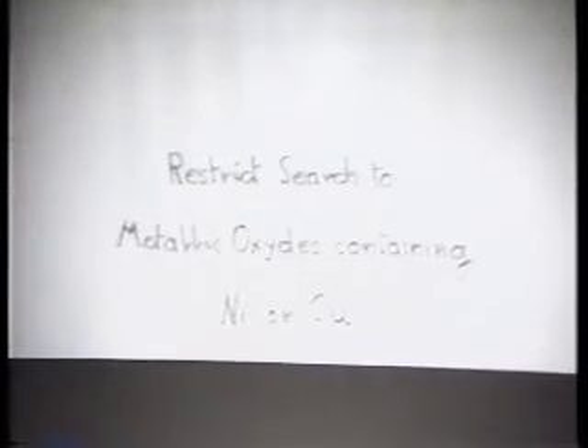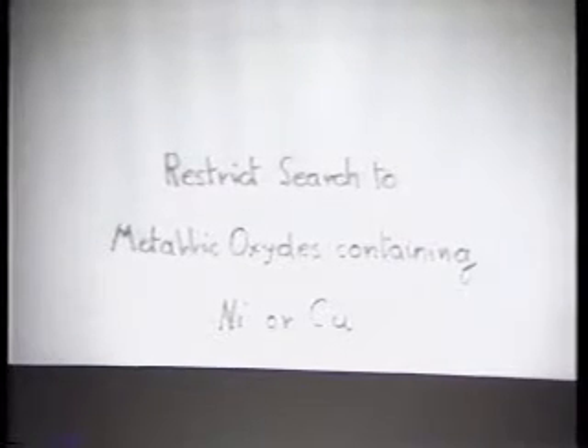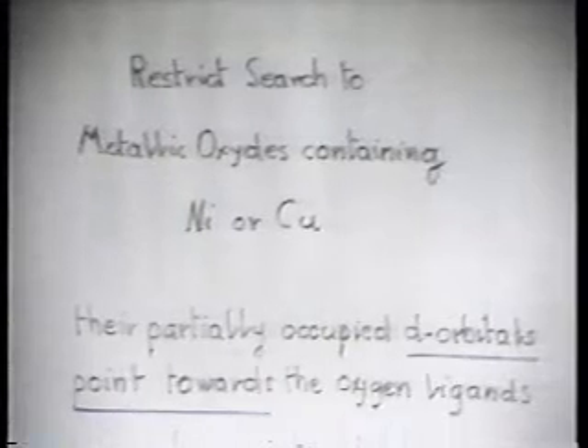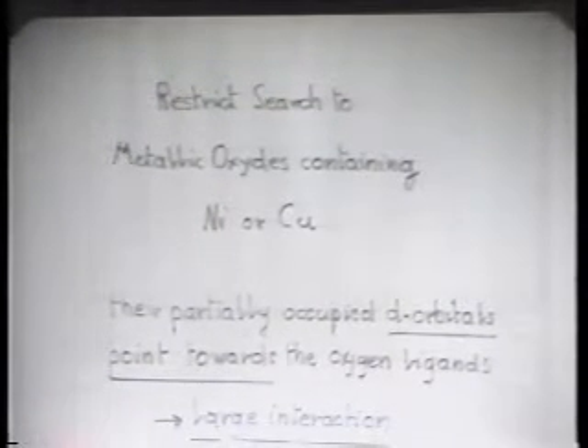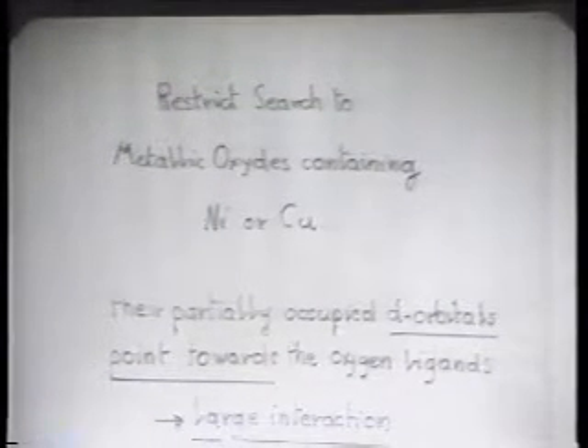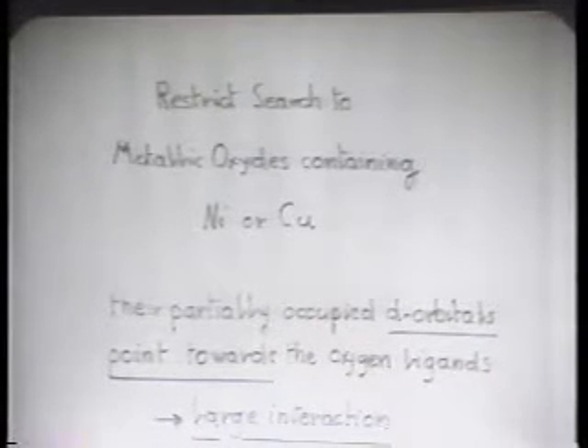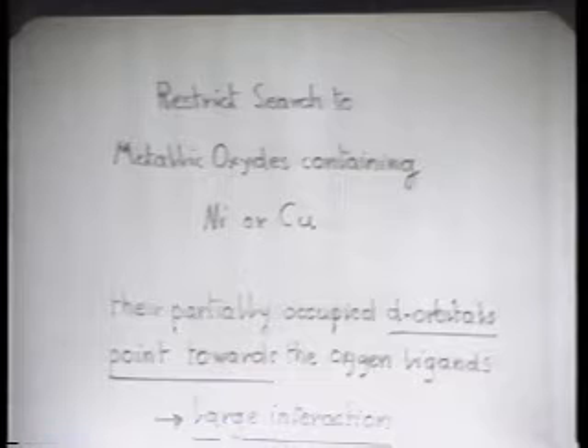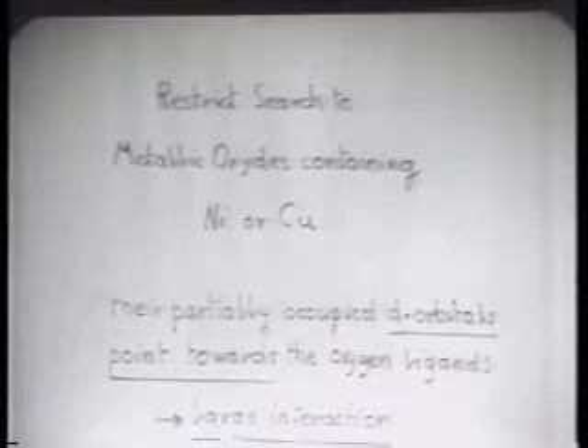The other part of the concept was to restrict our search strictly to metallic oxides containing nickel and copper only in octahedral coordination. Why? Because they have partially occupied d orbitals which point toward the oxygen ligands. And therefore, this was our view, one would have a large interaction between the metal and the ligand.